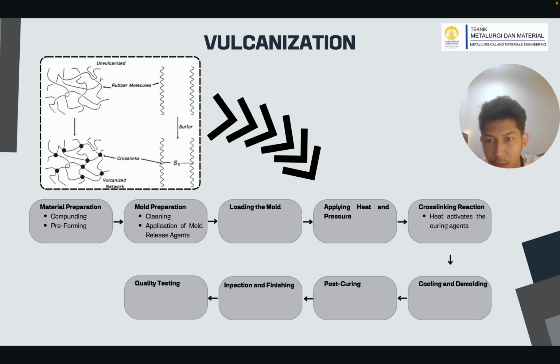The third step is loading the mold and carefully applying heat and pressure, at temperatures between 160 degrees Celsius and 200 degrees Celsius, depending on the fluorocarbon formulation. For pressure, typically high pressure from 2 to 6 megapascal is applied to compress the material and fill the mold completely, ensuring the proper shape and surface finish.